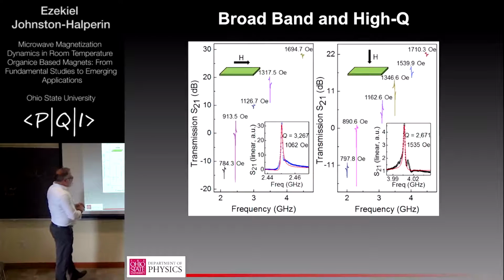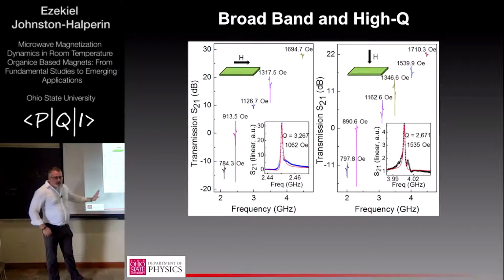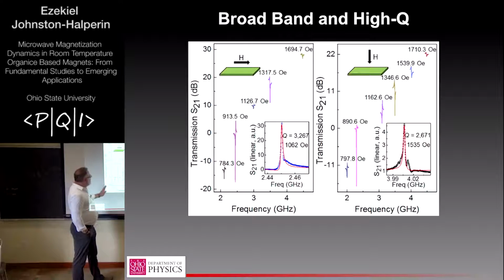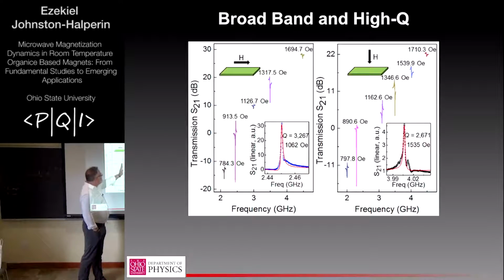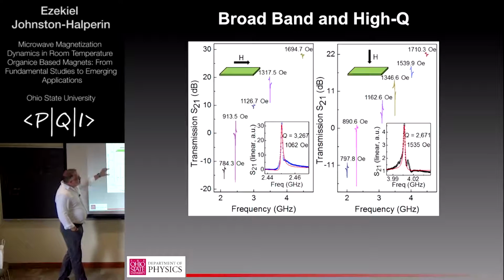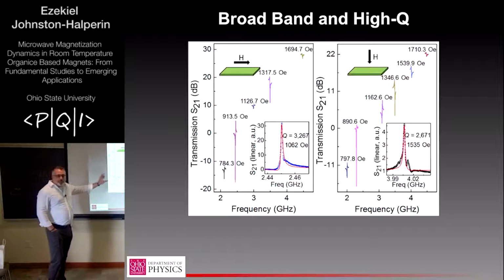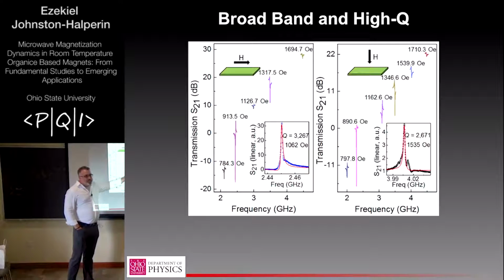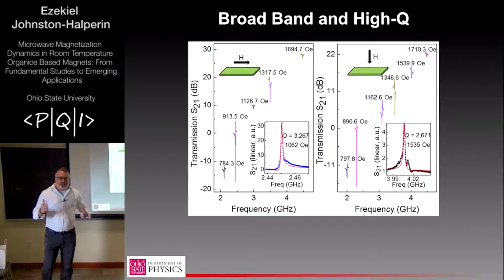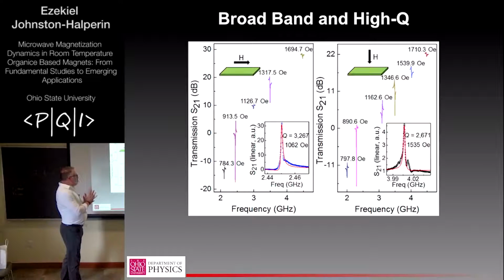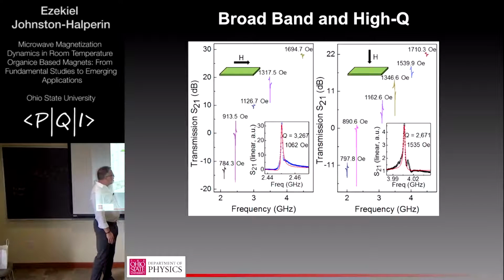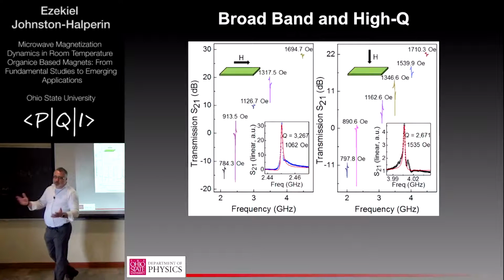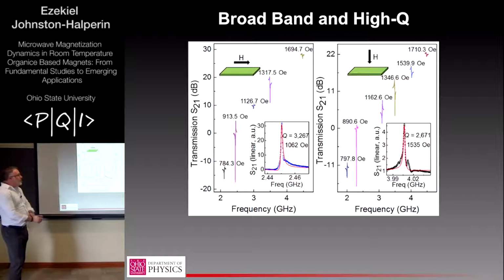That allows us to now do broadband FMR. You can see these very sharp resonances persist across a wide frequency range. The difference in amplitude here, I'm still unpacking a little bit. It's not clear yet if that's intrinsic to V[TCNE] or just has to do with the measurement circuit being better and worse coupled. But these Q of 3,000 or 2,000, depending on the different field orientation in plane and out of plane, are comparable to the one Gauss line width regime.